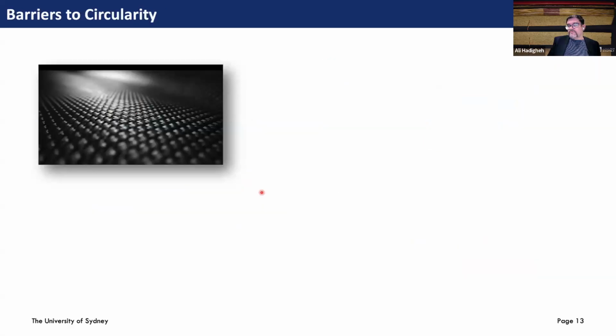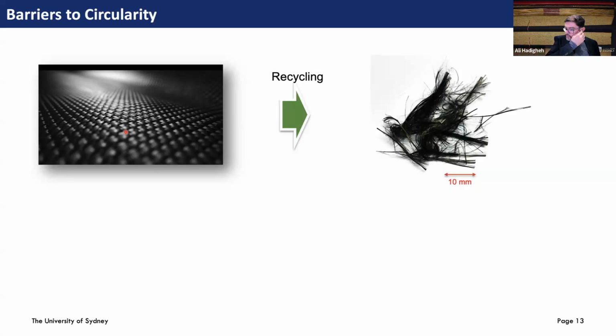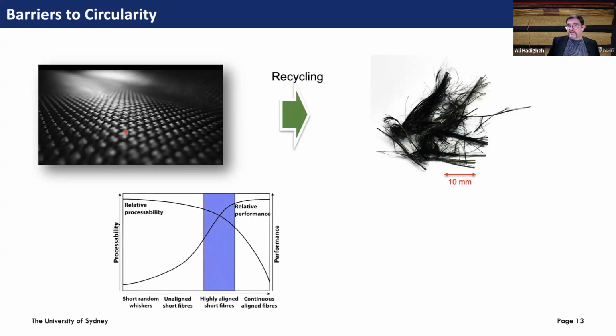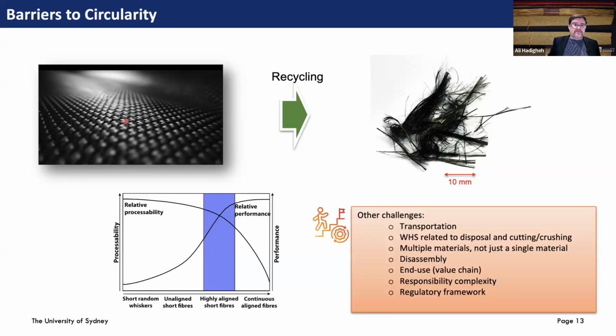But if we look at all these recycling methods, the biggest challenge is that when we have virgin composites, you're basically dealing with very well aligned fibers, nicely continuous and in perfect condition. But when we do recycling, you deal with such a scenario. So you have short fibers, you have randomly distributed or mostly entangled fibers. So how do you deal with that? And if we look at the performance of these aligned fibers and randomly distributed short fibers, you see the performance of those randomly distributed is very minimal compared to virgin aligned fibers. So there are a lot of challenges in this space. One of them is that alignment, the short nature of these recycled fibers.